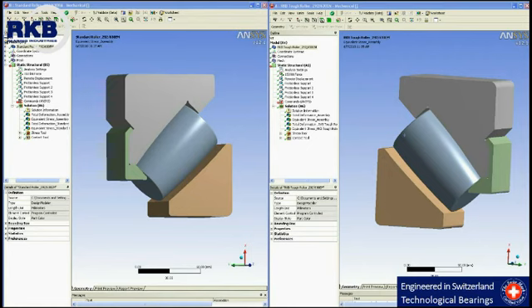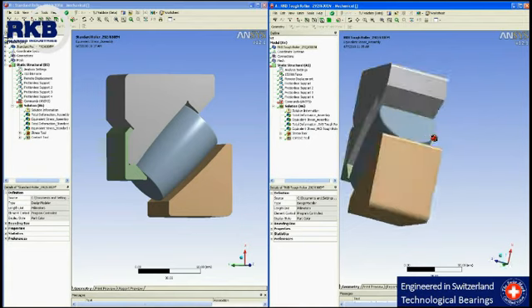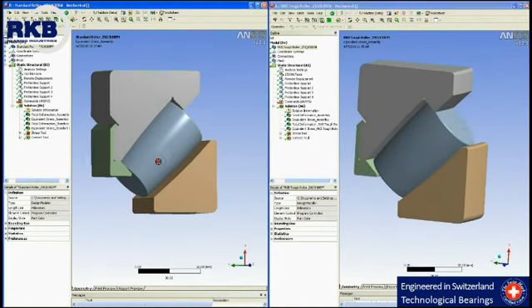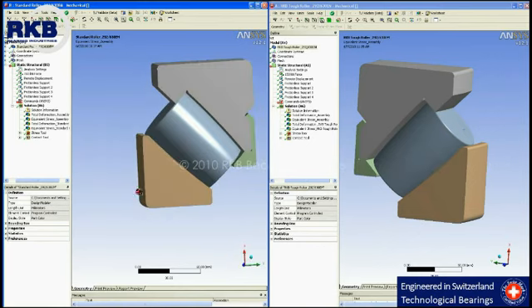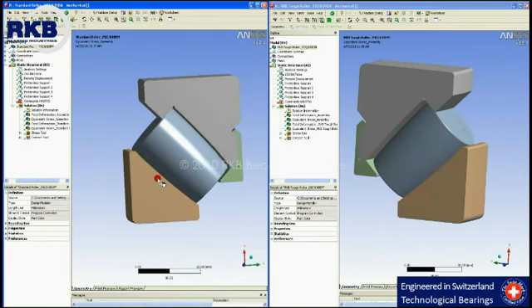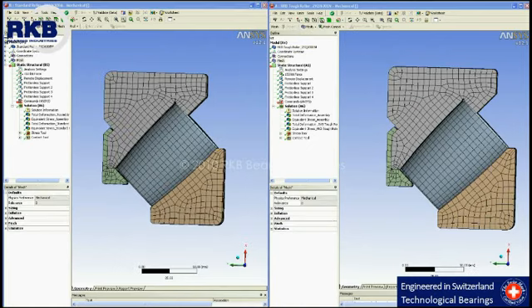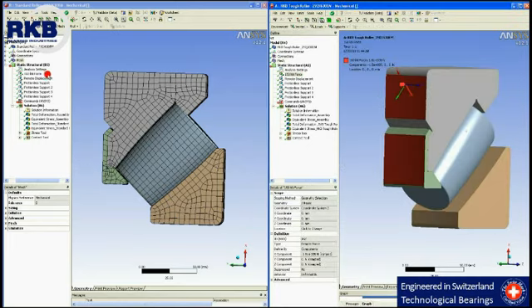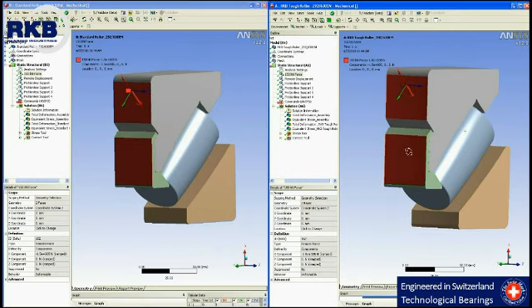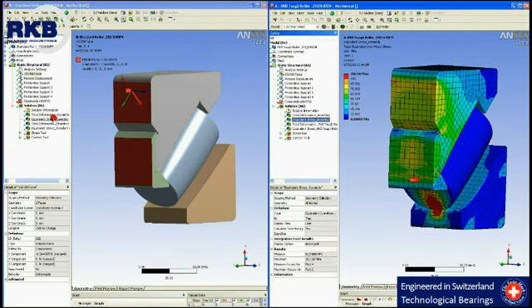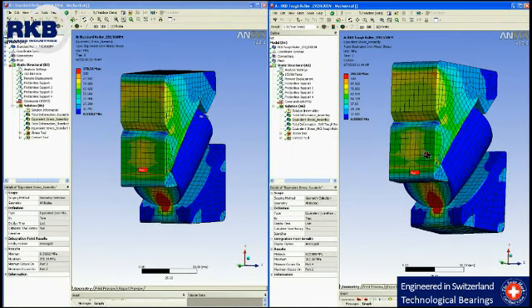To evaluate the benefits offered by RKB Tough Rollers compared to standard ones, we used finite element analysis in ANSYS environment. We analyzed an RKB Tough Roller and a standard roller from a thrust bearing 292630EM from the point of view of stress distribution, total deformation and safety factor. As is common knowledge, stress is equal to the ratio between the force and the section area to which it is applied. By applying the same force of 150 kN to both rollers, we obtain the same equivalent von Mises stress. It is of around 390 megapascals.